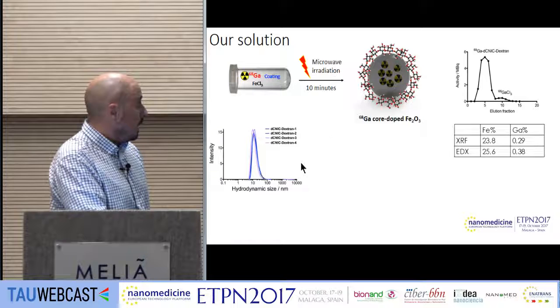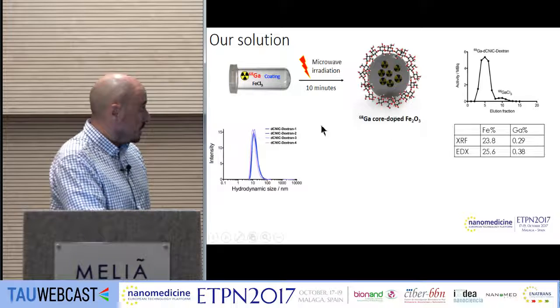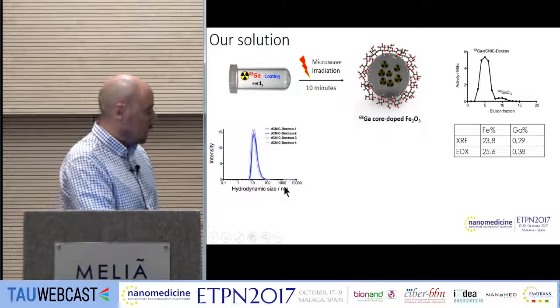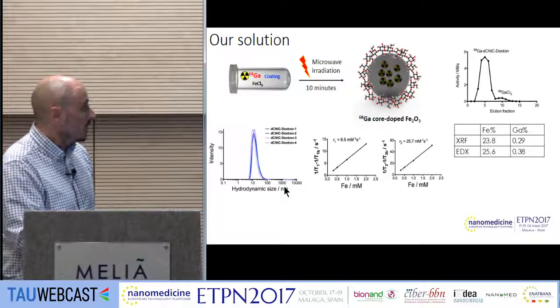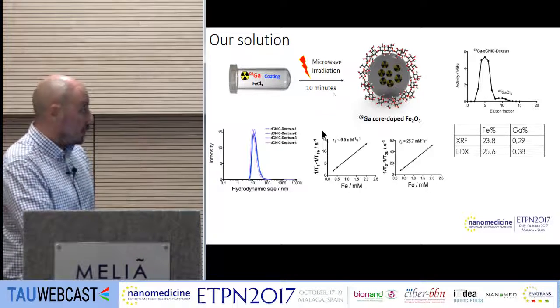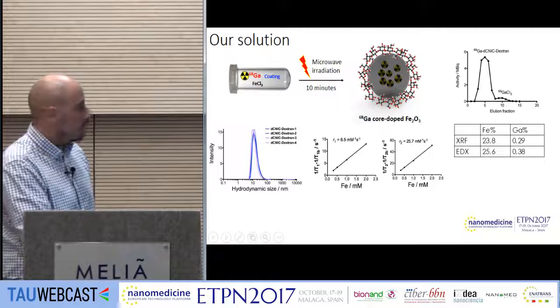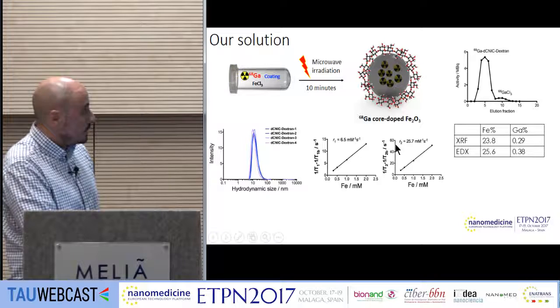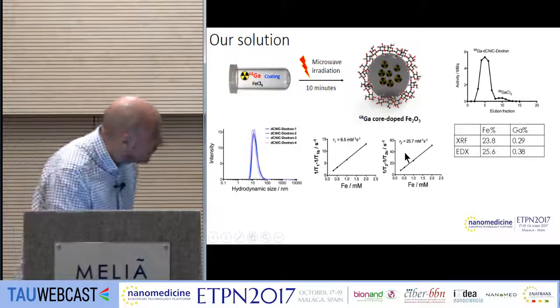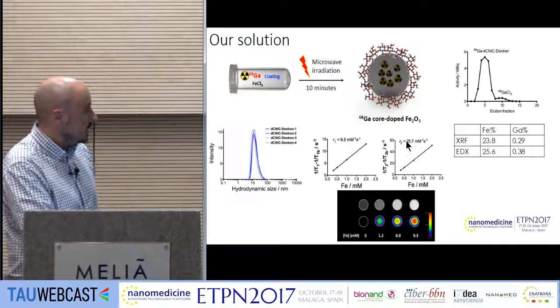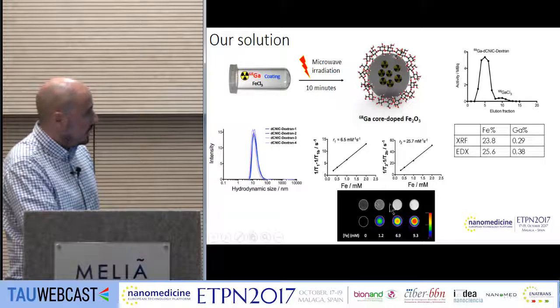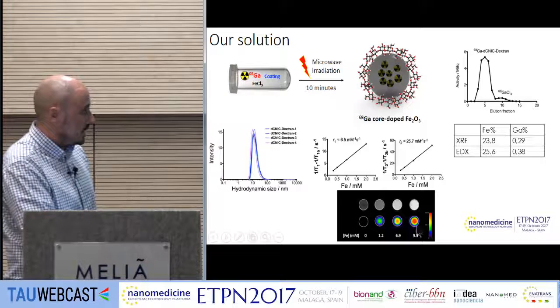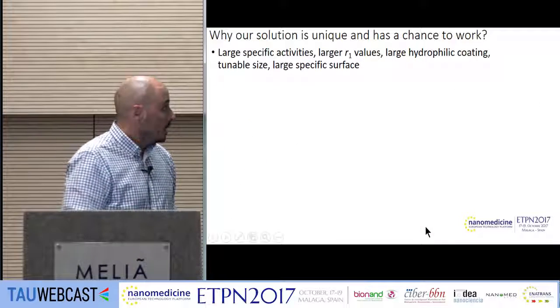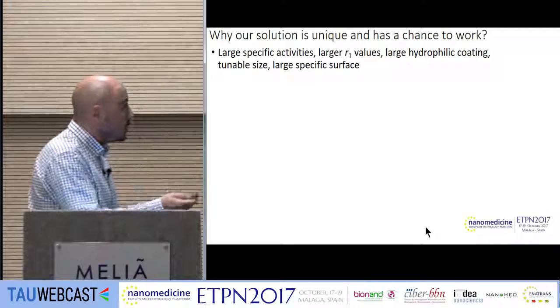This is the hydrodynamic size for 4 different syntheses of the nanoparticles, all exactly the same hydrodynamic size. We characterize the relaxivity because they are so small. They are more paramagnetic than superparamagnetic. They show a very large R1 value of 6.5 and a small R2 value of 20-something. You can see that in a phantom. The higher the amount of iron, the brighter is the signal in MRI, and the larger is the signal in the PET. So why is our solution unique?